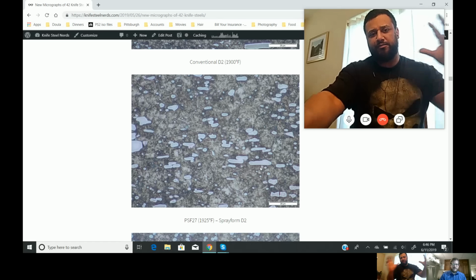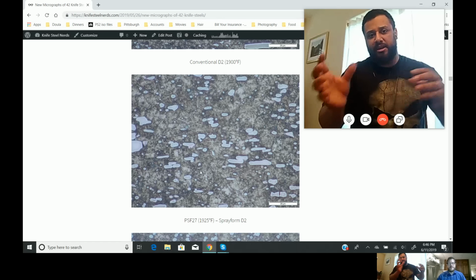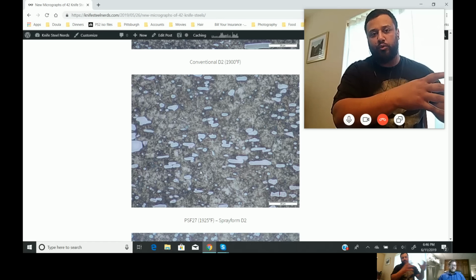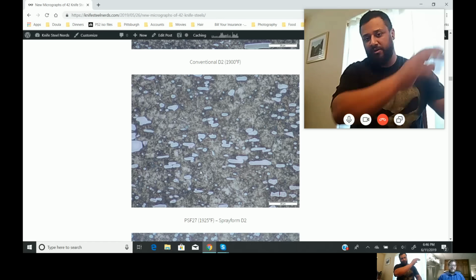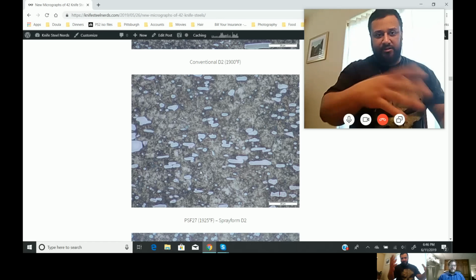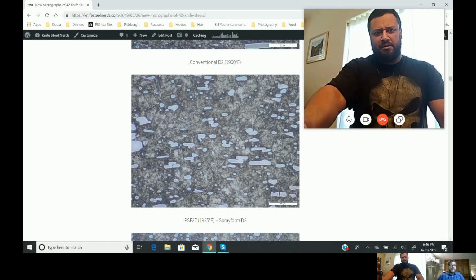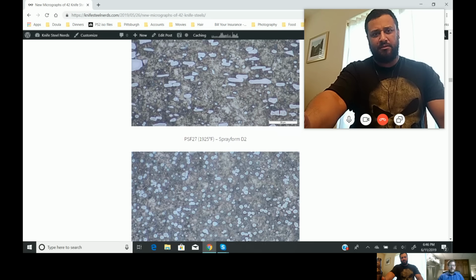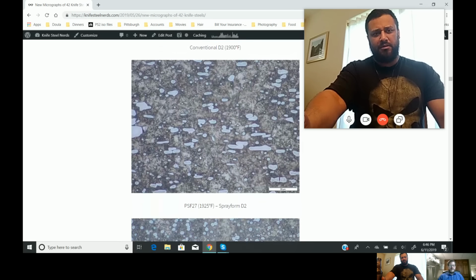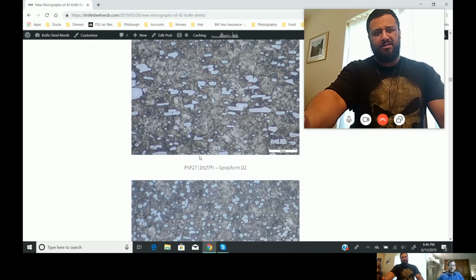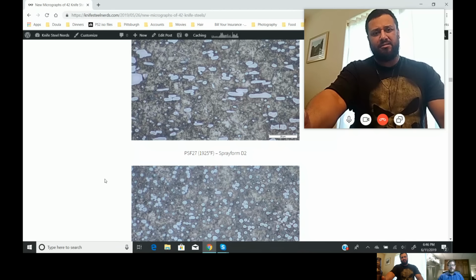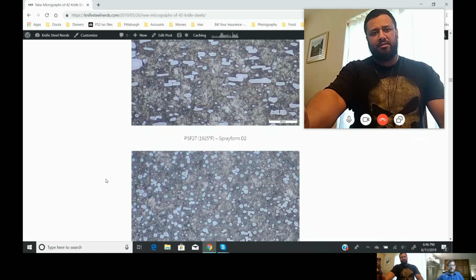It's definitely like spraying into an ingot, right? Not hipping it, not condensing powder that's been cooled and then recompressing that, but just spraying it directly into the ingot. It's definitely interesting. Not as good as powder metallurgy, but there are some intriguing things there. I wish there were more knife steels. These carbides are definitely more elongated, less spherical than the powder metallurgy. We'll see if any more steels come up, but spray form is almost as old as powder metallurgy, and it hasn't really caught on, so I don't see anything changing.